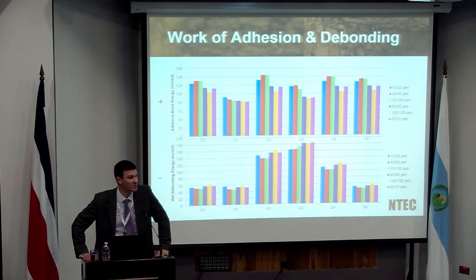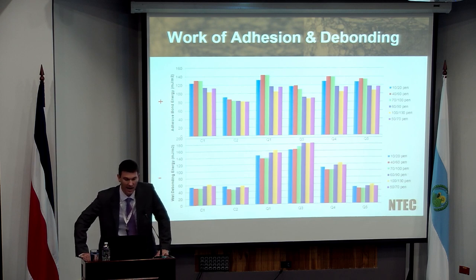So straight away, if you look at the bottom graph, we can see two of those material combinations, the ones in the middle, are giving us extremely high debonding adhesion values. In other words, they are really indicating that thermodynamically, water and aggregate would much rather be bonded together than the bitumen and the aggregate. And that obviously is a concern. If we're designing a material that needs to be resistant to the effects of water in our asphalt materials, high values of debonding adhesion or energy are going to give us pretty poor performance. So that would give you at least a starting point.